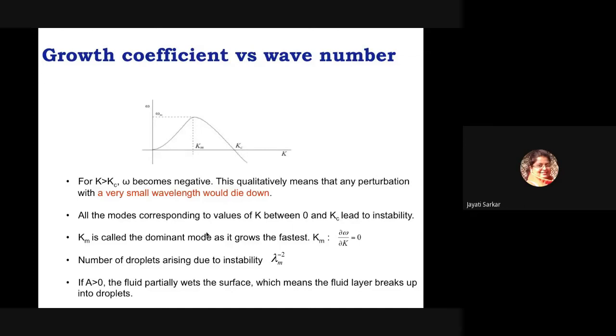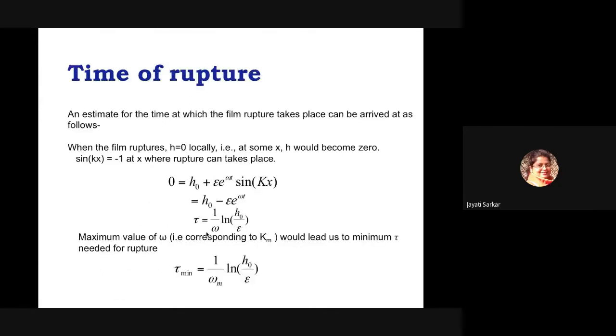So the spreading coefficient and the Hamaker coefficient are again negatively related. One can see that if A is greater than 0, the spreading coefficient is negative in that case, right? So that actually leads up to this dewetting. That is what is happening.